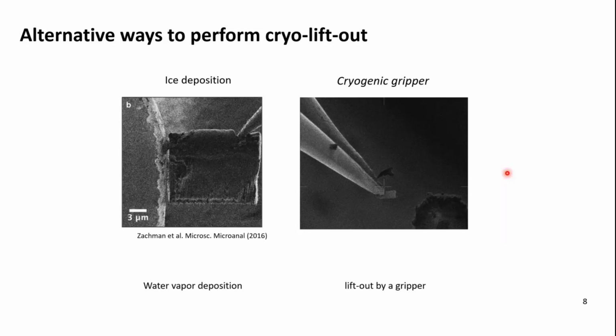There are other commercially available ways to do lift-out. First, you can use water vapor to deposit ice everywhere to weld your sample to the cold manipulator or half grid, or you can use a cryogenic gripper to manipulate your sample. And this method is still available at UPenn, but I'm more used to redeposition.